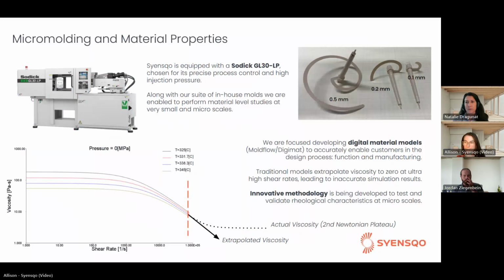Just as an example, if you look at traditional models for looking at polymer rheology, it's very common to see these multi-shear curves like what's shown on the slide here, where they taper off into an asymptote. And in fact, at very, very high shear rates, which is very common in micromolding type applications, polymers will actually realize a second Newtonian plateau. This is something that, speaking personally, was relatively new to me. And it's not always captured in the sort of models that you use for simulation. So we're also working on innovative methodology to measure this accurately and work it into our models. So that's just an example of the kind of things we're working on.